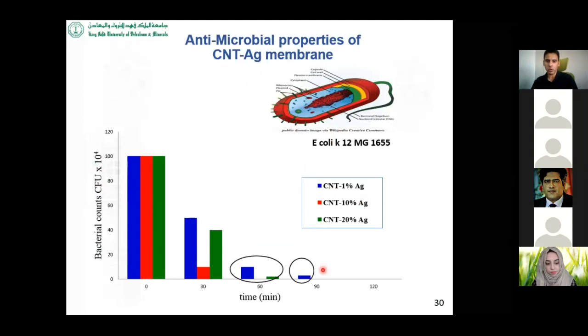Okay, so here these are different membrane with various loading of silver. We found that membrane with 10% of silver were able to kill this huge concentration of the bacteria in just 1 hour. So, which is really a great achievement. And by the way, all the membrane were able to kill the bacteria in 2 hours, but this one shows the most attractive feature. Of course, there are reasons for this. I will not go in detail, but just I want to highlight this. These membrane have excellent antibacterial potential.